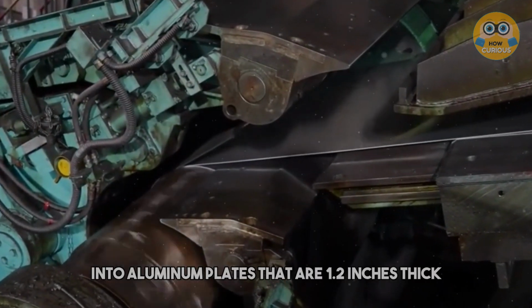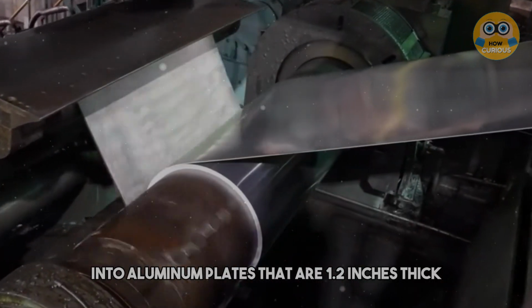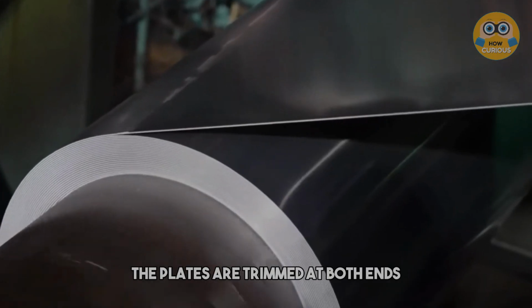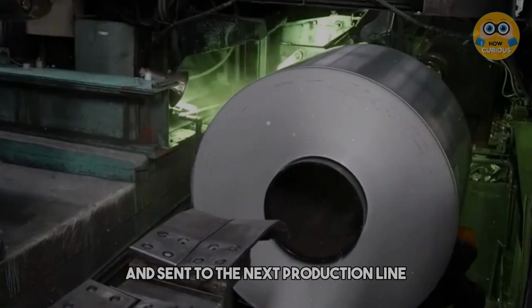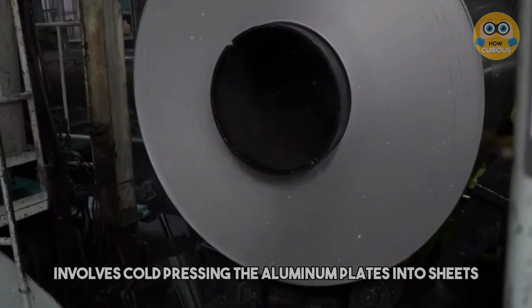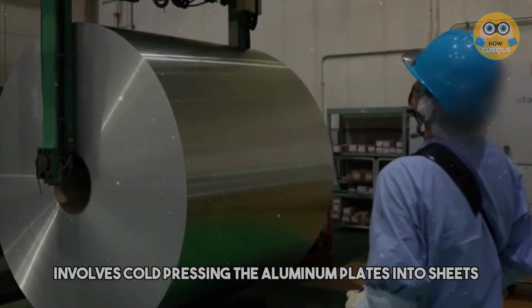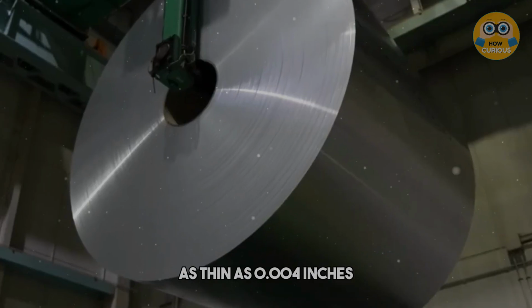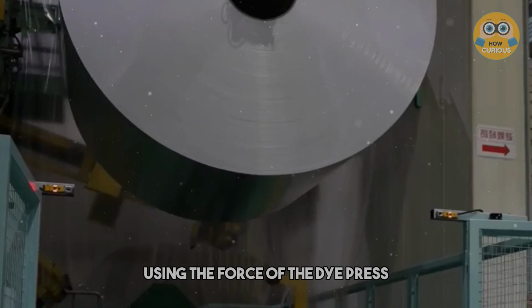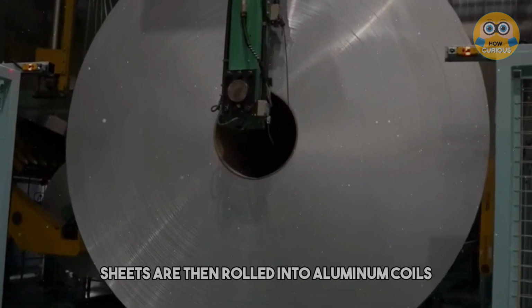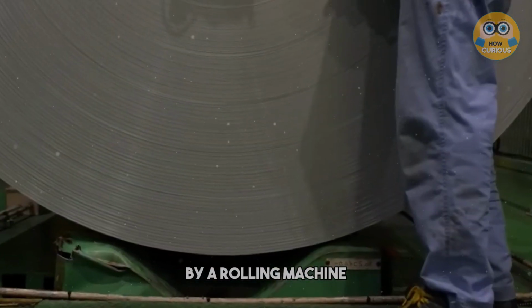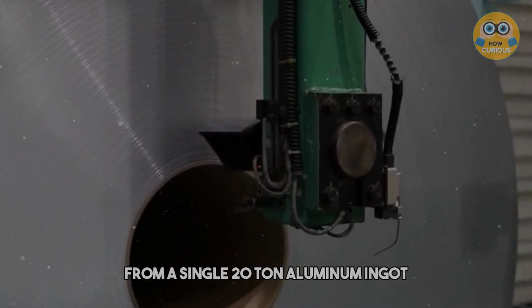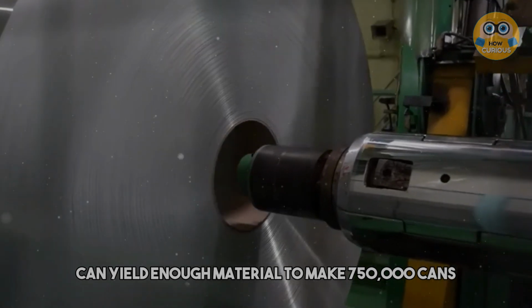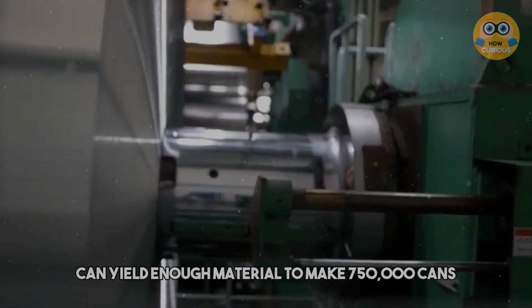Once pressed into aluminum plates that are 1.2 inches thick, the plates are trimmed at both ends and sent to the next production line. This processing line involves cold pressing the aluminum plates into sheets as thin as 0.004 inches using the force of the die press. The sheets are then rolled into aluminum coils by a rolling machine. From a single 20-ton aluminum ingot, this coil production can yield enough material to make 750,000 cans.